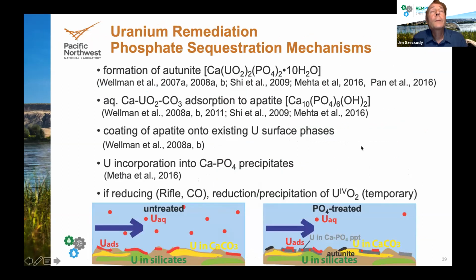And there's been considerable work done with phosphate reaction with uranium, and there are multiple mechanisms that have been identified, from direct formation of autunite, which is a calcium uranyl phosphate, to forming apatite, which then aqueous uranium adsorbs to.